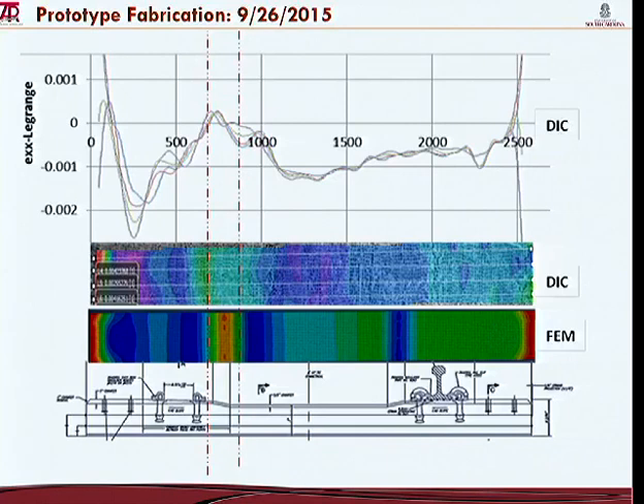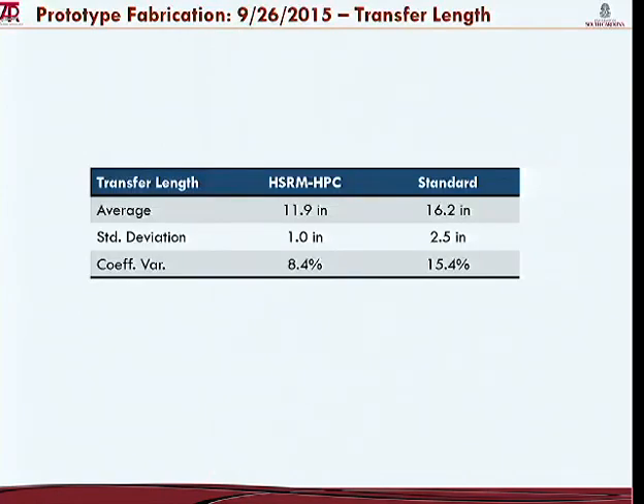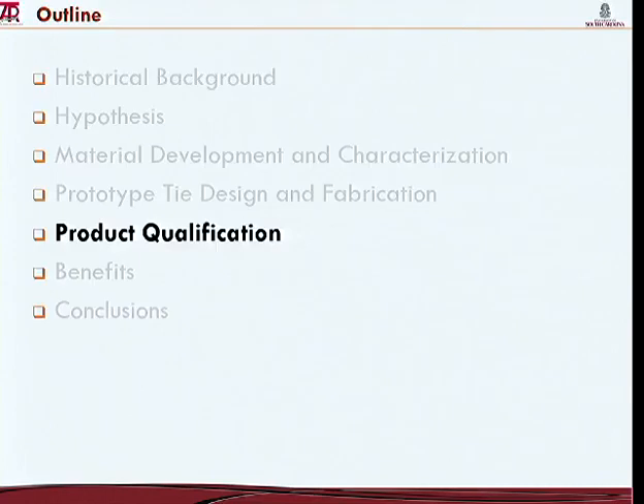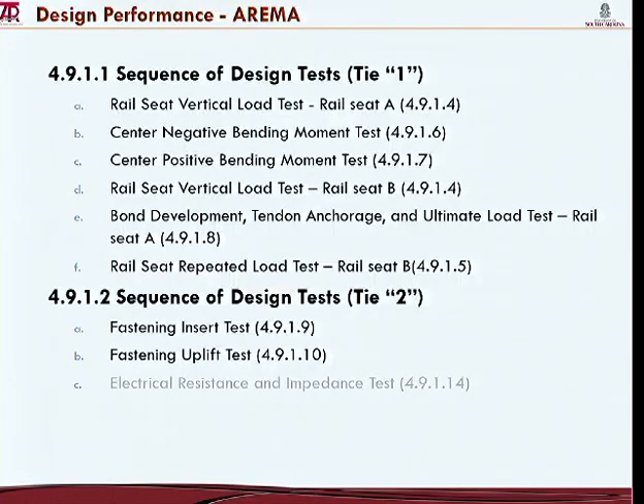We see these effects. Nevertheless, we were able to compute transfer lengths, and it seems that the high-strength reduced modulus ties did produce shorter transfer lengths than the standard ties, and also with a better coefficient of variation. And these measurements were not only from our DIC measurements, but were also measured by an independent contractor who was there at the time, using a different DIC system, and also Whittemore gauges. So the product was qualified, following all the standard AREMA tests here.